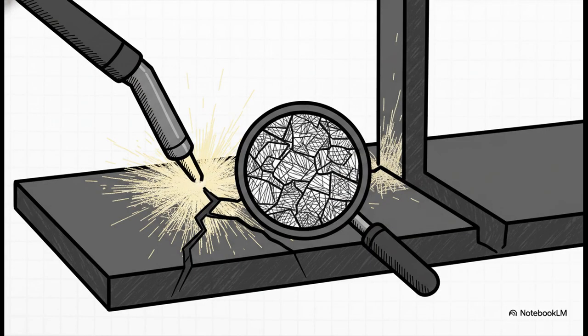The hidden metallurgical damage caused by a simple, careless arc strike outside the weld groove is severe. When you accidentally strike your arc on the parent material out there, you cause rapid, localized heating and high-rate quenching. This literally changes the steel's molecular structure, turning it into an untempered, super brittle martensitic microstructure. It makes the metal prone to snapping like glass. To a strict inspector, an arc mark isn't just a surface scratch. It is a major crack initiation site and an instant, non-negotiable failure.